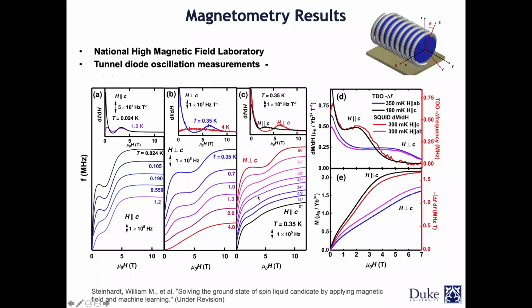But the key, which we didn't see in our other measurements, is that there is an anomaly happening. It's not as sharp as you would expect for a long-range ordering, but there is something happening. If you look at the field, say from 2 Tesla to about 4 or 5 Tesla, there is definitely something going on. And it is only at low temperatures; when we start to warm it up, it starts to wash away. So it shows that whatever it is, it has a quantum mechanical nature to it.